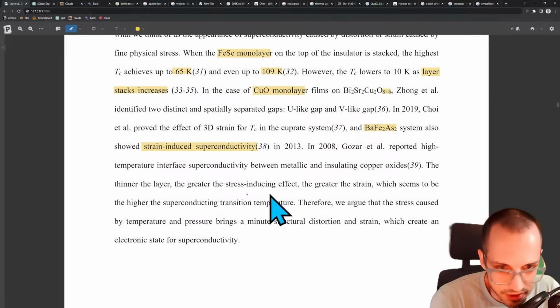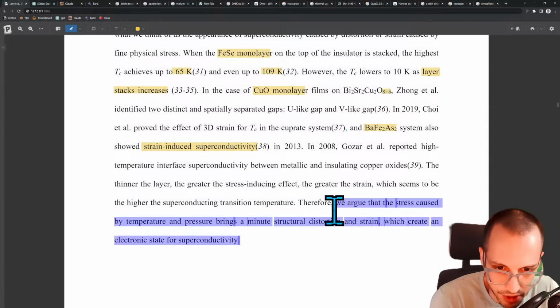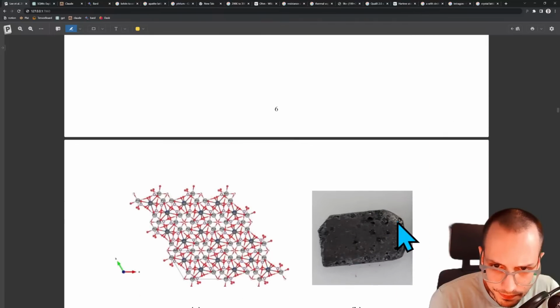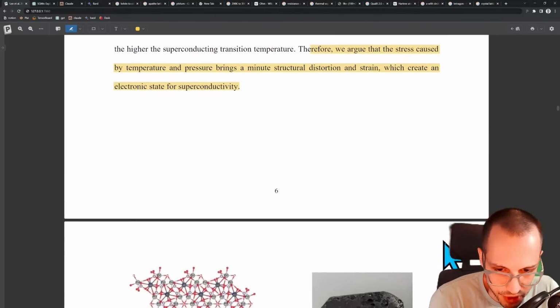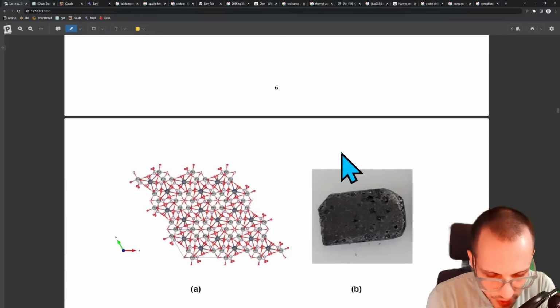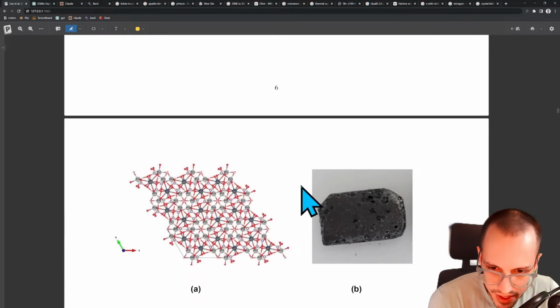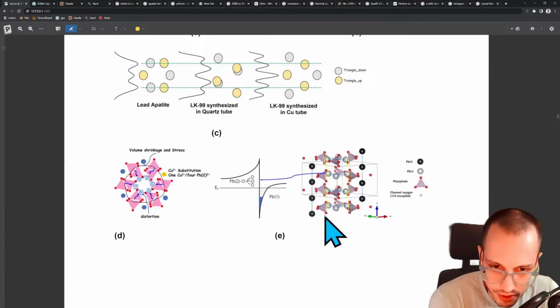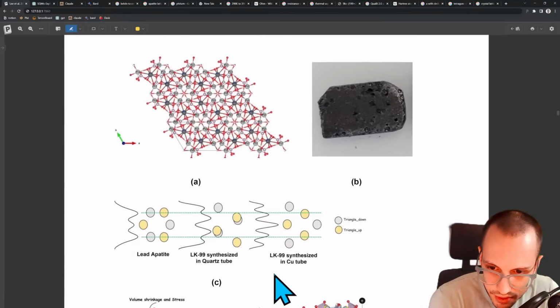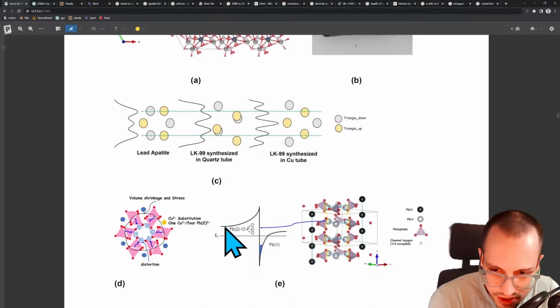Okay, back to this. The thinner layer, the greater the stress-inducing effect, the greater the strain, which seems to be the higher the superconducting transition temperature. Therefore, we argue that stress caused by temperature and pressure brings a minute structural distortion which creates the electronic state for superconductivity. Okay, so basically people have been twisting metal, straining it, and they've been lowering the temperature in order to get superconductivity. So what do we got here? We got a figure, A, B, C, D, and E.